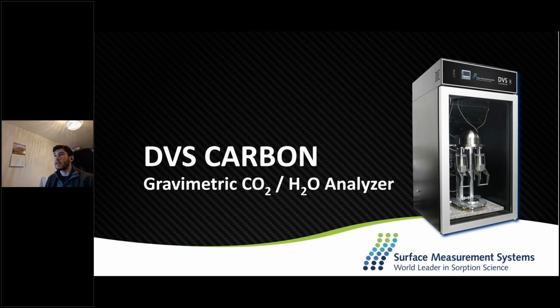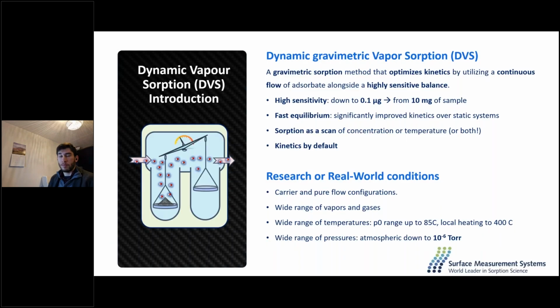The DVS carbon is a dynamic gravimetric vapor sorption instrument. For those not familiar, gravimetric means that there is a microbalance which measures the weight of an adsorbate as it takes up mass. It takes up mass as it absorbs either CO2 or water. The reason it is dynamic is because there is a constant flow passing above this adsorbate, which means that it optimizes kinetics and it leads to a faster equilibrium rather than a point-based method.